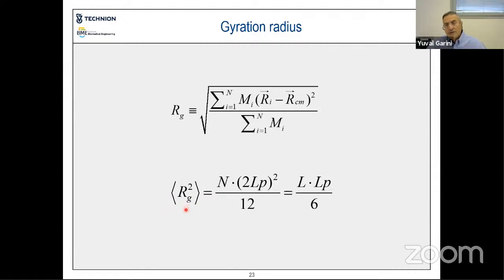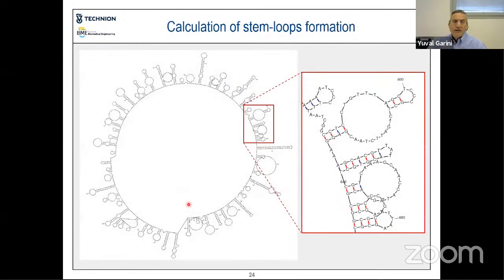And of course, when you do an experiment, you work on many structures, you get a distribution. So what we did here, first of all, again, we calculated the stem loops. You can see that there are many stem loops formed along the single-stranded ring DNA in this case. You can see the zoom in.